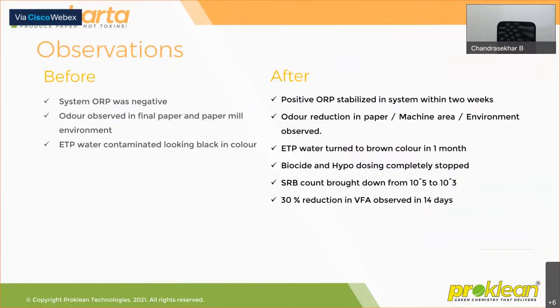What are the observations we have seen after just a couple of weeks? When we started, the ORP was negative. ORP moved to the positive zone and got completely stabilized in 2 weeks. The final paper odor which was there in the system came down, and the environment in the paper mill, which was very bad, significantly improved almost to nil. The ETP water, which used to be very dark and contaminated, started turning towards brown color. We completely stopped the biocide and hypo, and we've seen a significant reduction in VFA.